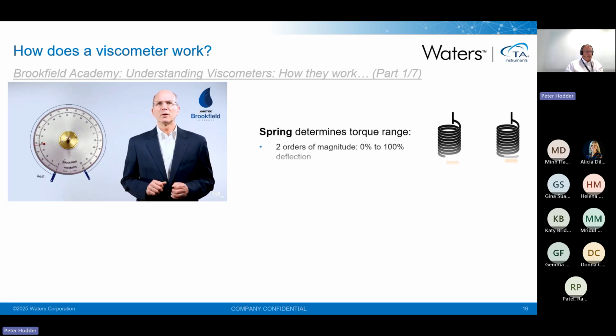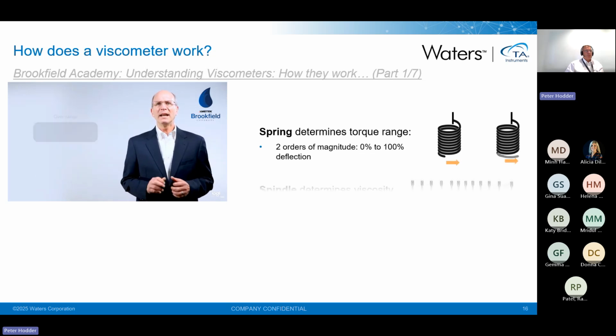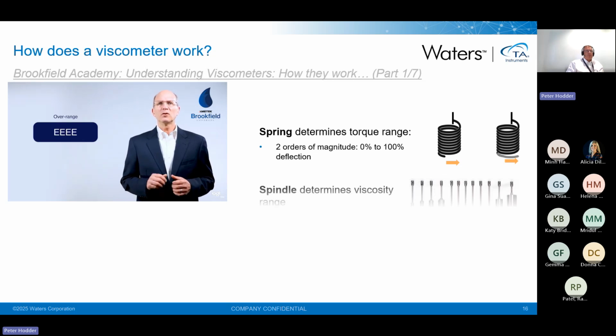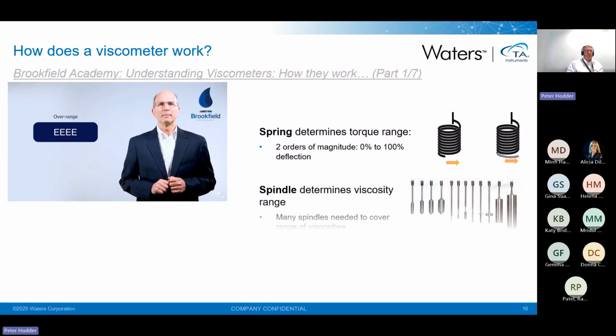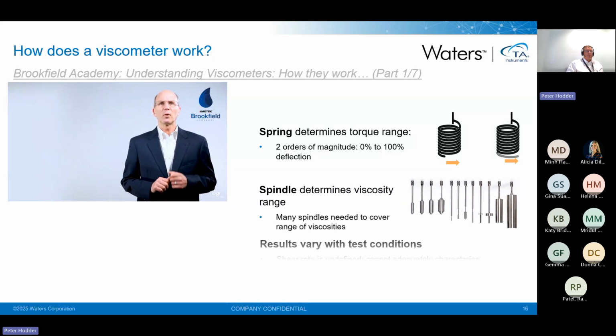0% is when the viscometer is at rest. 100% is when the viscometer is measuring at its maximum. Anything beyond 100% is an overrange. So when you see a viscometer with EEEE, it means that it went over the range or beyond 100%. EEEE indicates that the sample is too viscous to measure with the selected spindle, speed, and spring range combination.